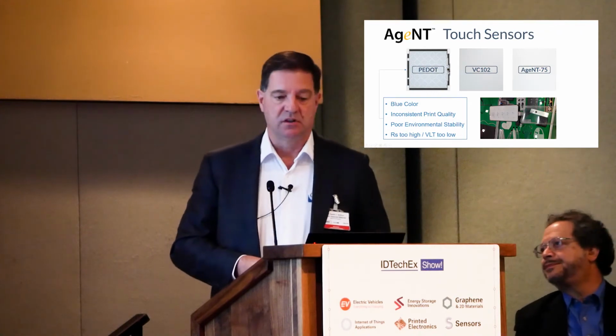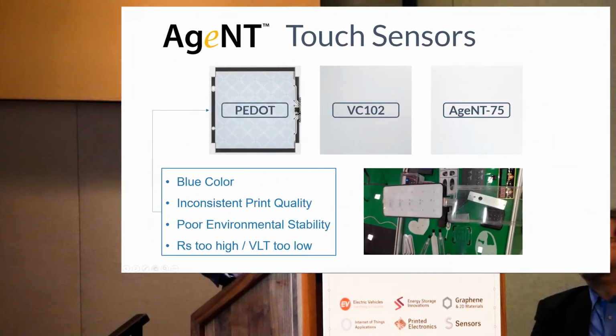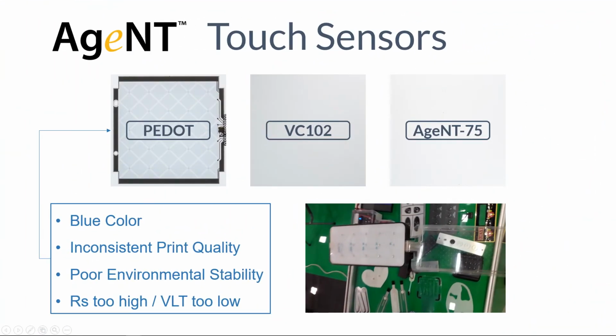So for touch sensors, we see PEDOT, not ITO, as the real enemy. And we are focusing on exploiting the pain points associated with PEDOT: blue color, inconsistent print quality, poor environmental stability. There's another pain point as well, which is that the sheet resistance and transparency properties of the PEDOT are not nearly as good as ITO and not nearly as good as silver nanowire and metal mesh.